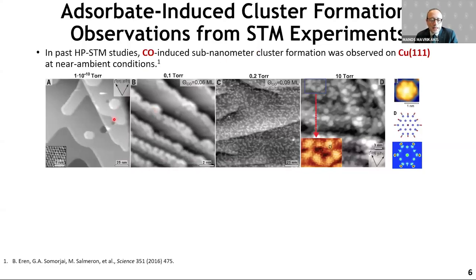So the results that were shown to me by Miguel and Gabor at the time are summarized in this series of snapshots, four snapshots. All of this is scanning tunneling microscopy. They have one of the world record performing instruments of high pressure, and by high pressure, I mean up to 10 torr. For those not familiar with these units, 760 torr is one atmosphere, so it's still below atmosphere.